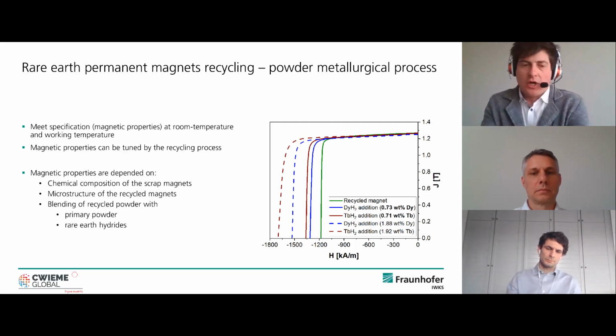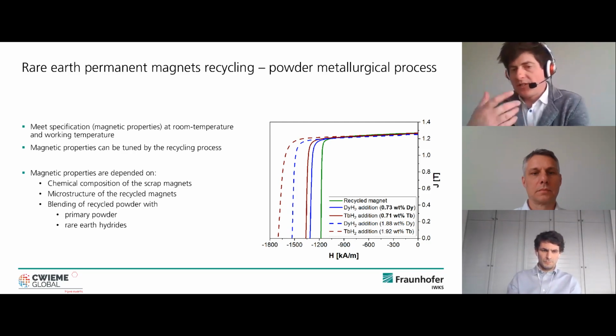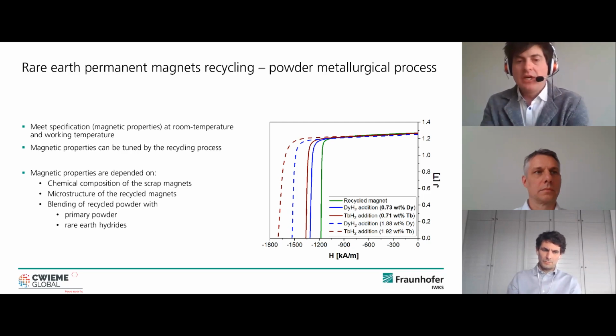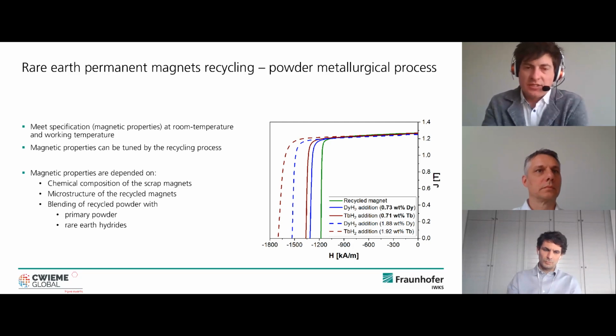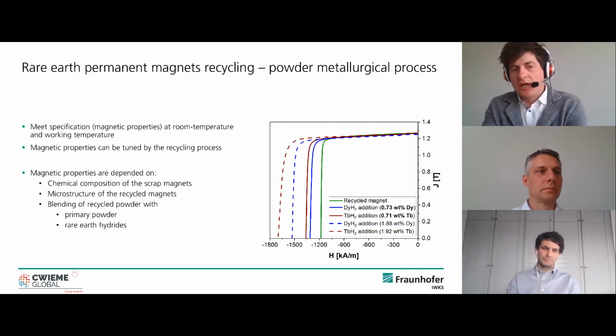When you have some eddy current heat up, for instance, you can have higher temperatures. The motor is operating at temperatures above 100 degrees C, you can have some demagnetization and the motor can't be used anymore. Therefore, you want to have a high coercivity. And all of that you can tune by the recycling process. You can work with the chemical composition of the scrap magnet. You can work with the microstructure of the recycled magnet. You can put some additives inside.